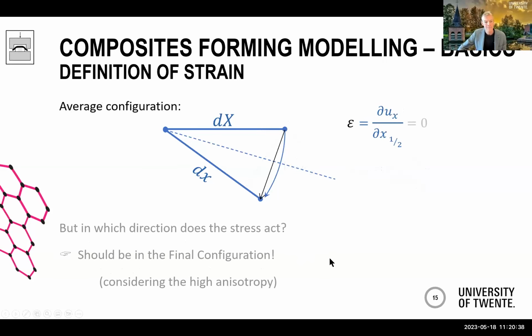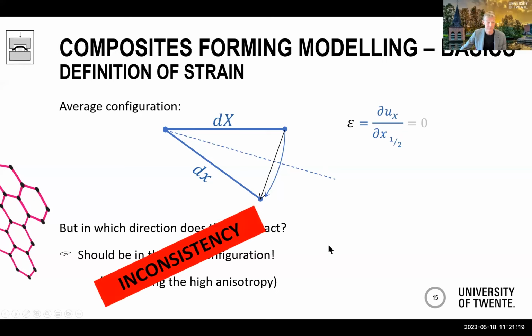However, if we think about the stresses, suppose this element has an initial stress already, then in the deformed situation, this stress should act in this particular direction, in the lowercase x direction. So the stress should be in the final configuration, certainly considering the high anisotropy. So, okay, we need to evaluate the strain in the average configuration and the stress in the final configuration. And that's just inconsistent as far as I can see. So what's the effect of that?